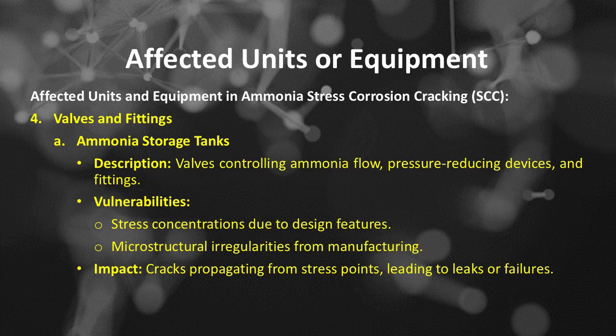Number 4 of affected units and equipment in ammonia stress corrosion cracking is valves and fittings. These are valves controlling ammonia flow, pressure-reducing devices, and fittings. The vulnerabilities of these valves and fittings include stress concentrations due to design features and microstructural irregularities from manufacturing. The impact would be cracks propagating from stress points, leading to leaks or failures.